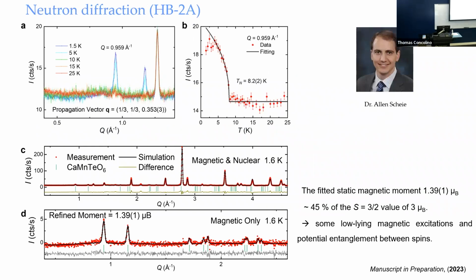So here's Alan. Here is the neutron diffraction data using a beamline, and you see the material undergoes a long range magnetic order around 8 Kelvin. And here the magnetic structure can be described by the propagation vector a third at 0.353. So from here you can see that it is an incommensurate magnetic ground state. And here the refined moment is 1.39, which is consistent with the low temperature heat capacity that I showed you earlier.